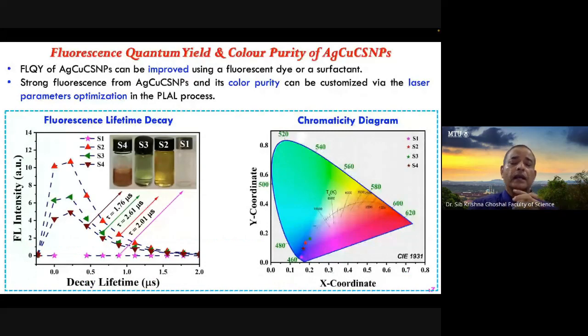Now, when we look at the color purity, where this emission is exactly happening, where this surface plasmon resonance is exactly happening, we need to do the CIE chromaticity mapping, the CIE chromaticity diagram. As you can see on the right-hand side, the CIE chromaticity diagram tells us three dots are in the blue-purple region. And this pure color, blue-purple region, is the highest frequency for these nanoparticles that we can use for therapeutic applications, for antibacterial and antimicrobial application.